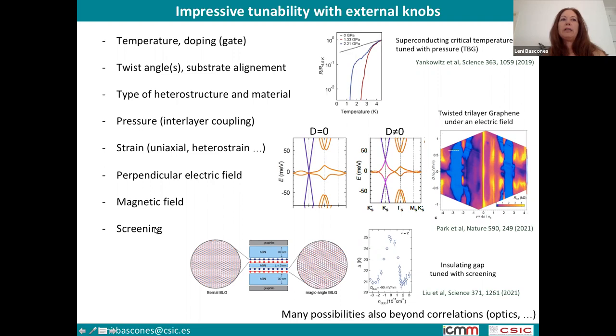And screening is another way in which we can play in this system, which is less obvious in other correlated materials. So for example, here you have an example of what's possible to do. This is twisted bilayer graphene here, and they have placed a bilayer graphene, and then by charging, doping this bilayer graphene, they modify the interaction here. And so they have been able to tune the insulating gap.